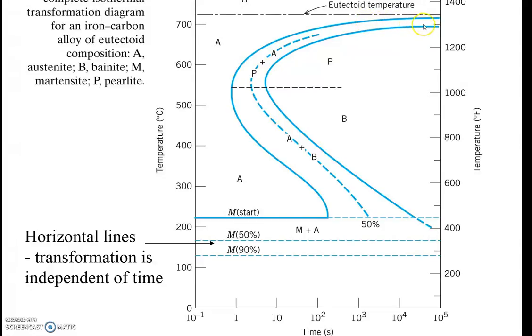Why do you get coarse-grained pearlite? At the higher temperature, you have a higher diffusion rate. Remember, you have alternating lamella of alpha ferrite and cementite, and they grow because of the diffusion of carbon. So with more carbon diffusing, you get thicker layers, a coarser grain.